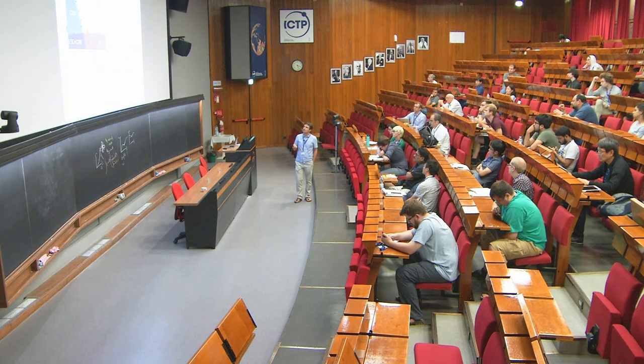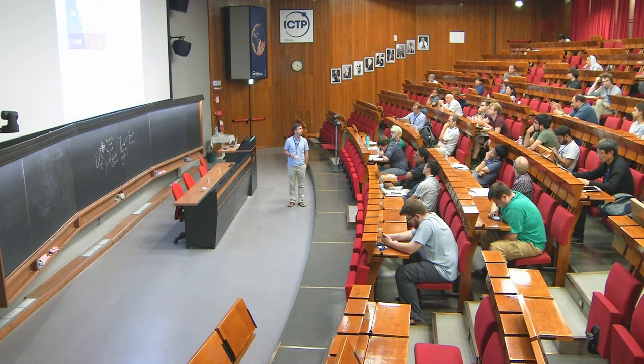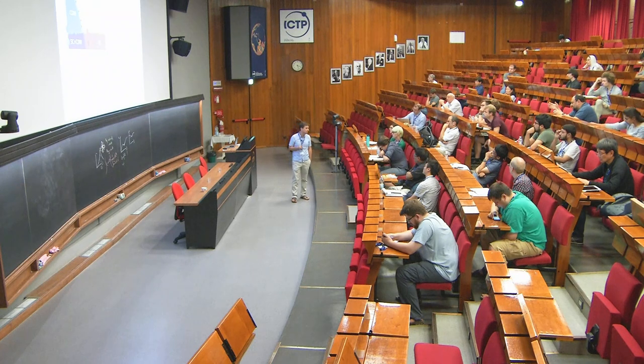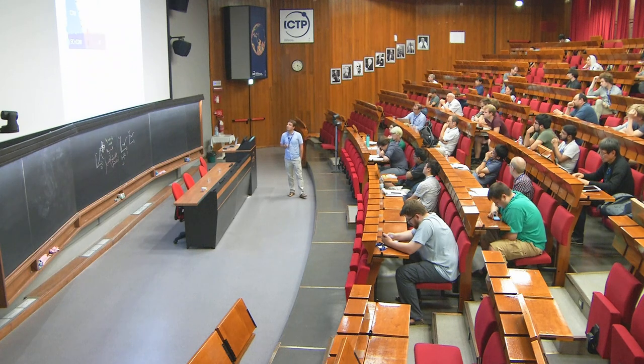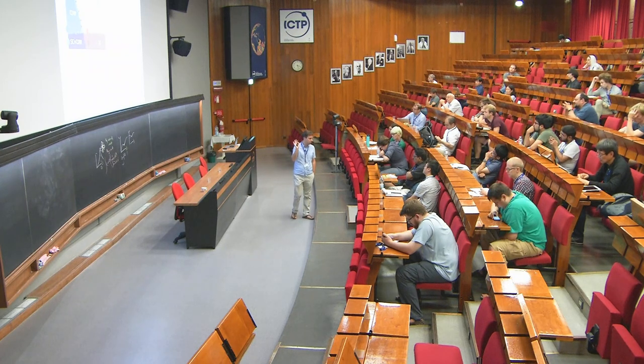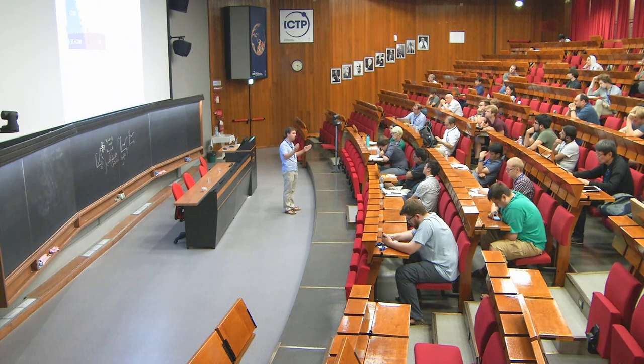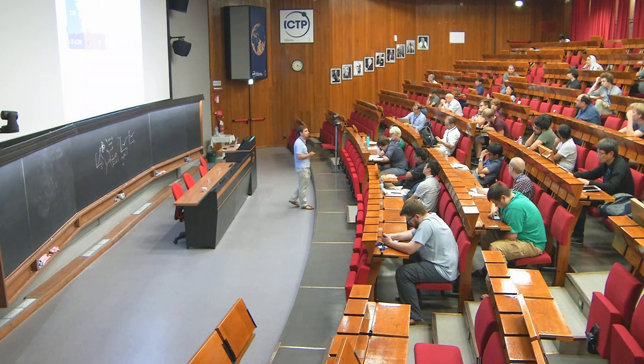Yeah, okay, so of course, you would need an independent measurement of the superconducting gap for that. But the Higgs mode, if you look at this sharp mode here, it softens as a function of pressure. TC is flat, so presumably it doesn't change much, 10% at most. There is one way of explaining it, which cannot be unique: as you kill the charge density wave state, the amplitude mode of the charge density wave state becomes closer and closer to the gap, and this pushes down the gap to lower frequency.